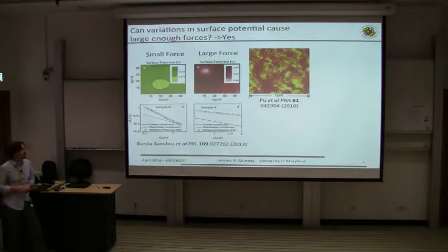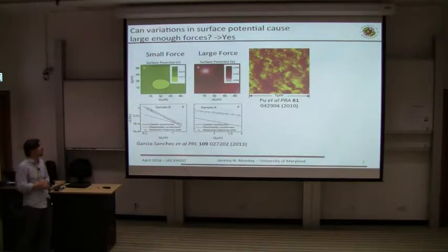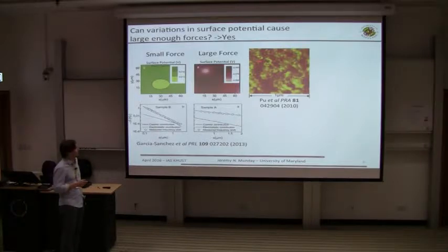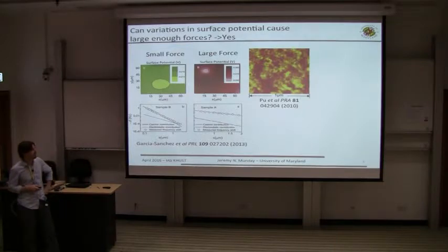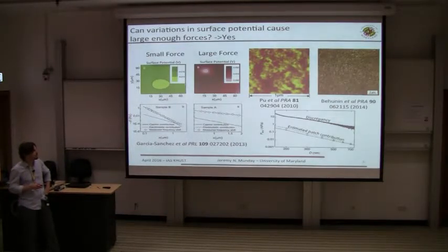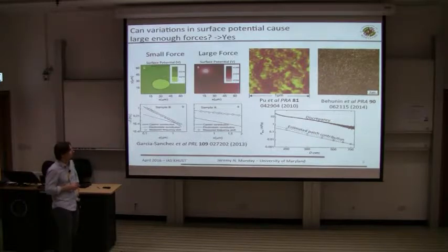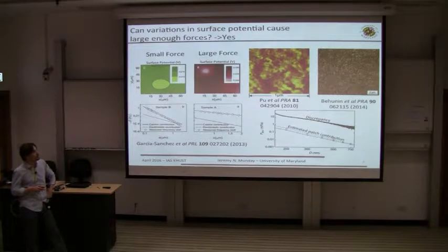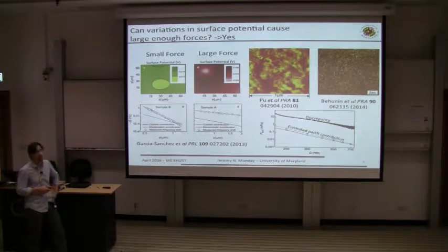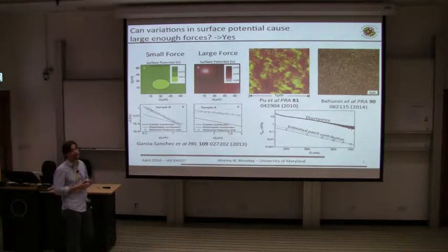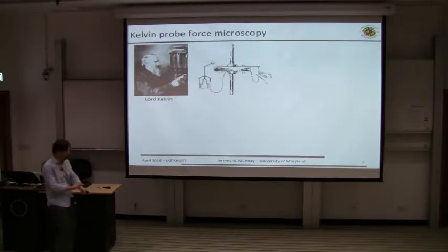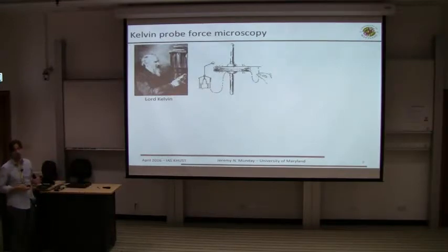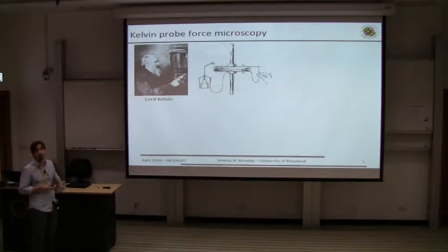This has also played a role in some atomic physics experiments, looking at patches in metal surfaces and how that can modify ionization of atoms as they approach a metal. And then recently there was work analyzing metal surfaces for Casimir force experiments. In this particular work, it was found that the electrostatic patch potentials were relatively small, and the effect shouldn't be influencing the forces. And so we wanted to see what this looks like for our experiments. We're going to be using a technique, which was also used in the previous ones, called Kelvin probe force microscopy.